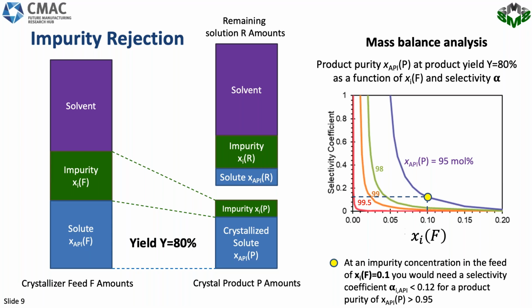You would use the solubility of the two components as a guide for that. So you check the solubility of, in this case, it was ibuprofen in the solvent. Yeah. And then the solubility of BPE in the solvent, and you then take a certain reference temperature, say 25 degrees or so, and you make a solution with the saturation concentration at 25 degrees for both components. And that is the composition where you're most likely to form co-crystals.